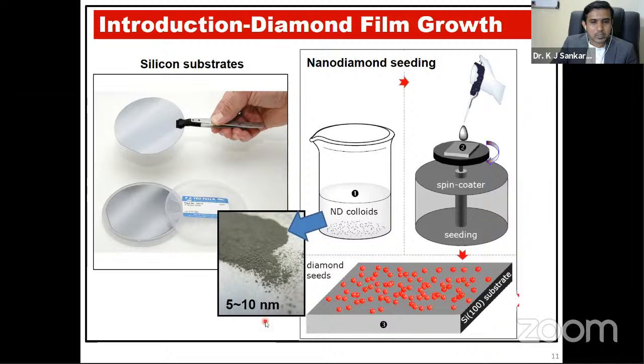These are the commercially available nano diamond particles, with a particle size of 5 to 10 nanometers, and we make nano diamond colloids, a suspension in distilled water. Then we drop those nano diamond colloids in a spin coater machine. This is the silicon substrate, and some drops of nano diamond colloids are placed on it. Once spin coated, you can see that the nano diamond seeds are placed on the silicon substrate. Here I mentioned the 100 substrate. If you use different orientations of silicon substrates, we can get different planes of diamond, but we are growing mostly polycrystalline diamond materials, not single crystalline diamond. So this is the silicon substrate seeded with the diamond seeds.